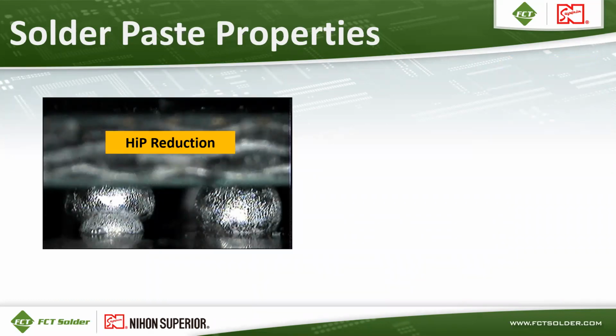Head and pillow is also a concern, and it's important to have a paste that can handle head and pillow or potentially prevent it. The way we would address that problem is making sure you have enough activity in the solder paste to hold up to, say, longer soak profiles and still have enough flux activity to remove the oxide from the solder powder and from the BGA sphere, and then give you a proper solder joint. But also important is a solder paste with a rheology that allows it to stretch, so it can maintain contact with the board pad and the BGA sphere if the BGA warps during reflow, which is fairly common for larger BGAs. That warpage can create a separation and create this problem all by itself. So if you have a paste that will stretch, with the proper type of rheology, it can minimize the potential for this problem.